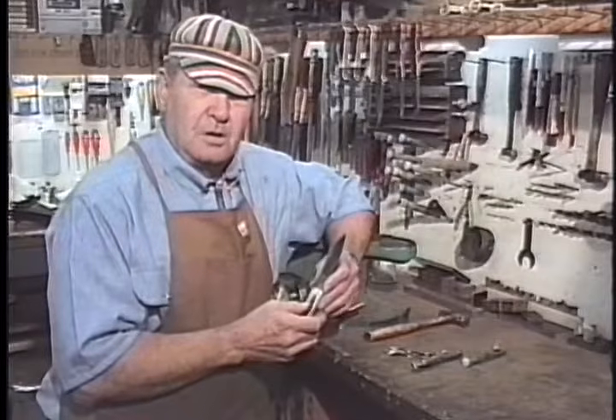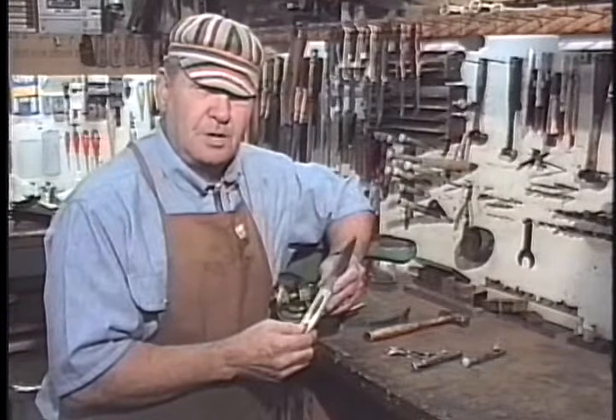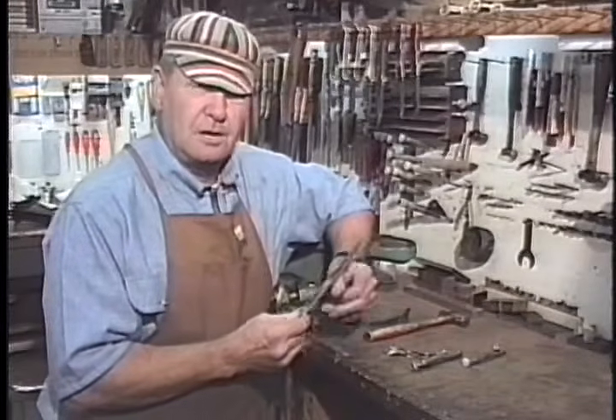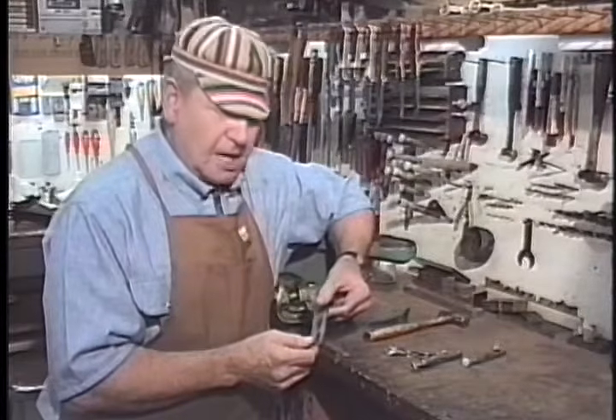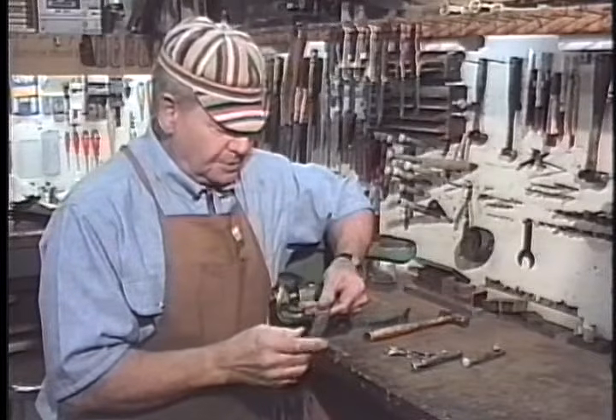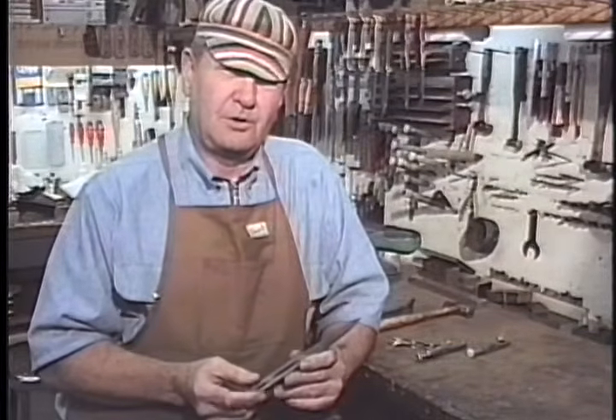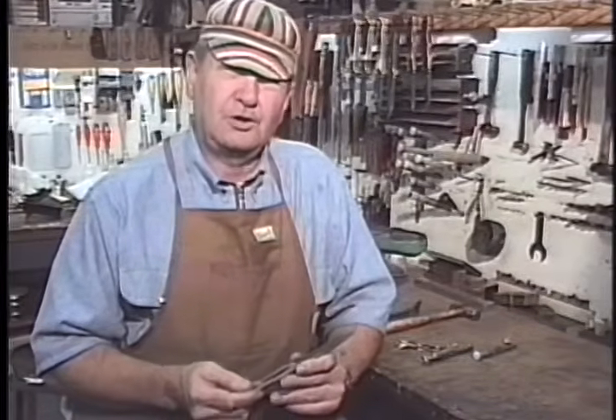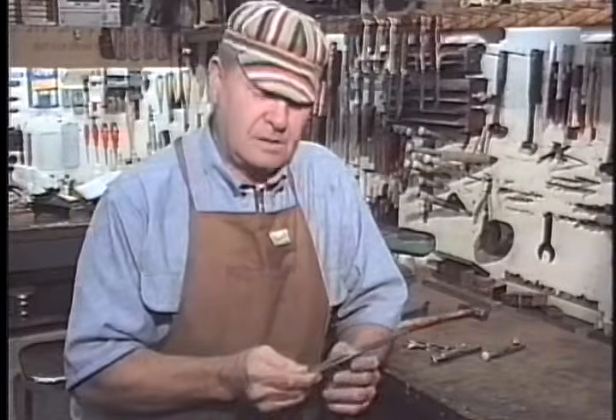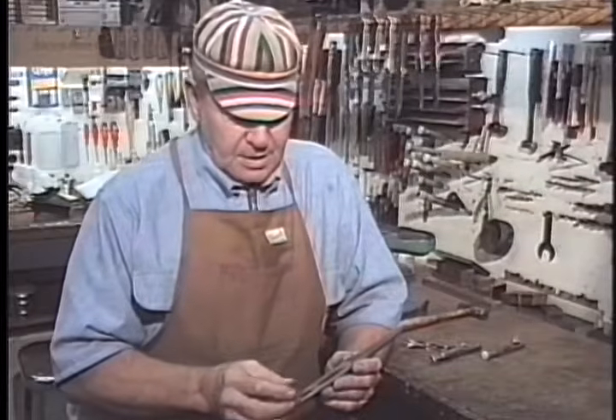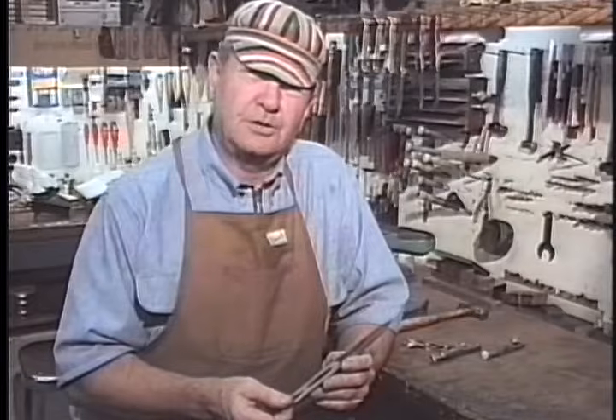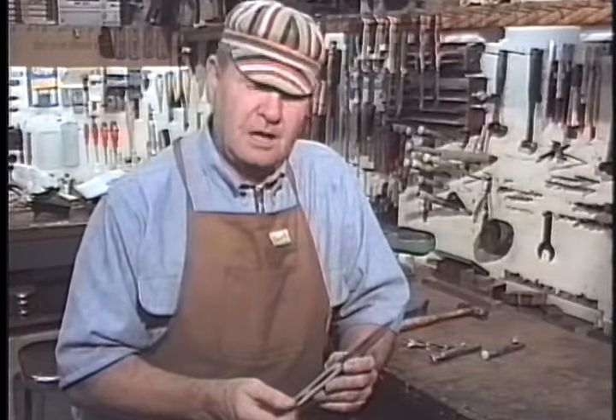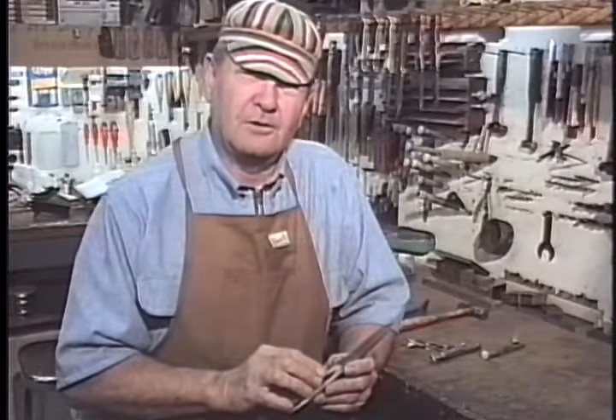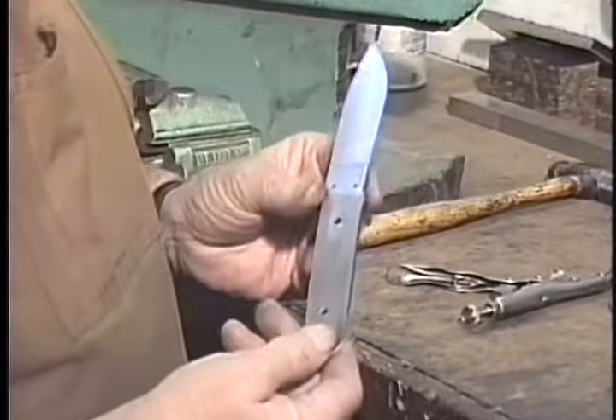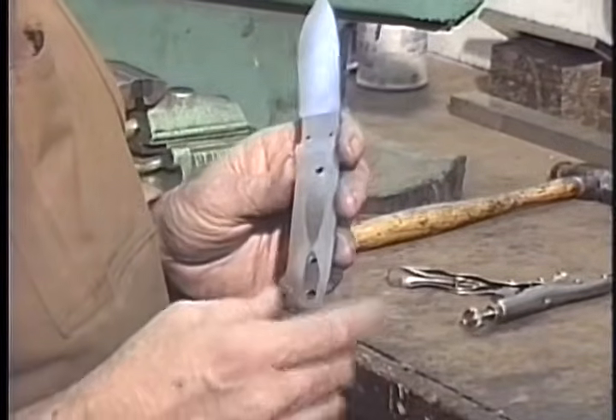At that point, it has to be chilled down to room temperature, and then it's put into a deep sub-zero chamber where it's taken down to about minus 200 degrees, depending on the shop you're using. At that point, theoretically, you've gotten all the martensite structure you're going to get out of this piece of tool steel. Now you take it out of that deep sub-zero and you put it into another draw furnace at 975 degrees for 2 hours. After the 2 hours, you take it out, you let it cool down to room temperature, then you put it right back in that draw furnace, bring it up to 975 for another 2 hours. Now this is the very famous, among heat treaters and toolmakers, 2+2 tempering draw that almost all high-speed steels get. It's one of the reasons why we get such great performance out of this particular alloy grade for a working field knife. There is no other alloy grade that'll work quite as well as this does for most of us.